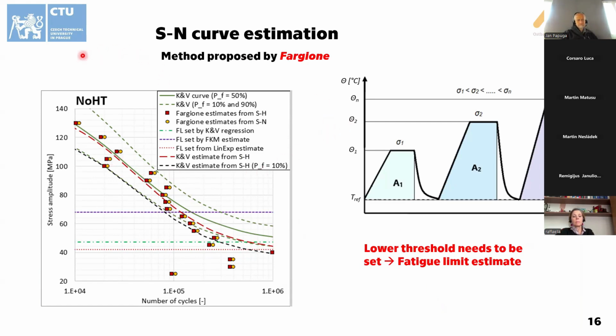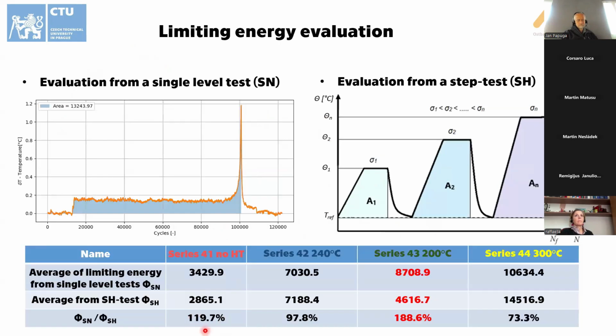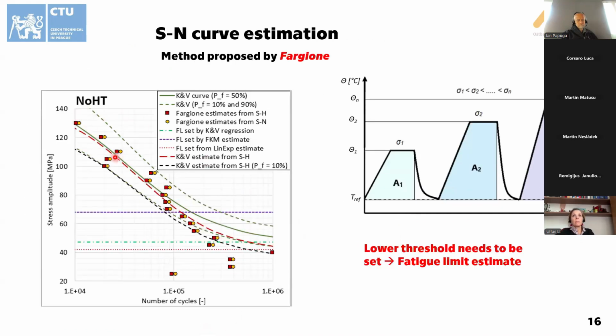And for the non-heat treated variant, as I'm showing here, if we use the Fargione method, we would find that there are not many differences between the limiting energy from the self-heating step test and the single level test, although it is more than 20% higher, but it doesn't correspond with the fatigue curve that much. But we can see that Fargione's method and the regression using the Kohout-Wichert regression, which is the red dashed line, show good correspondence to the green line, which is the experimentally set up non-heat treated variant.